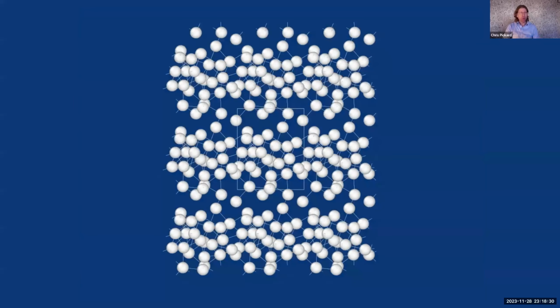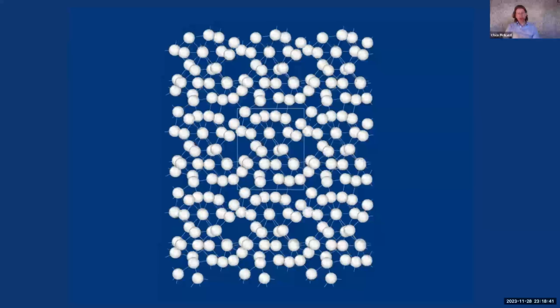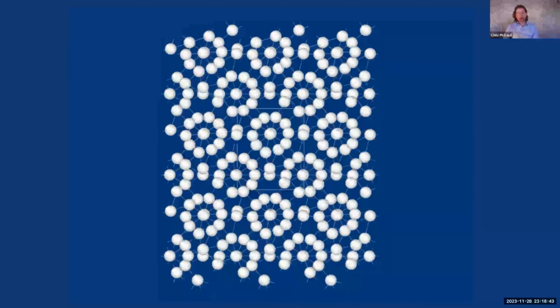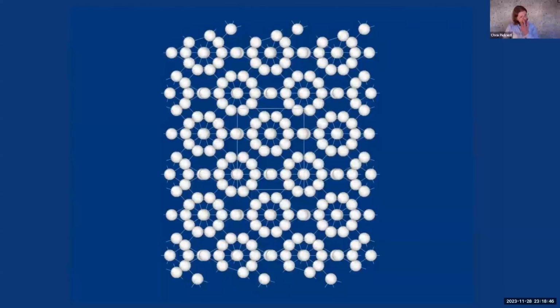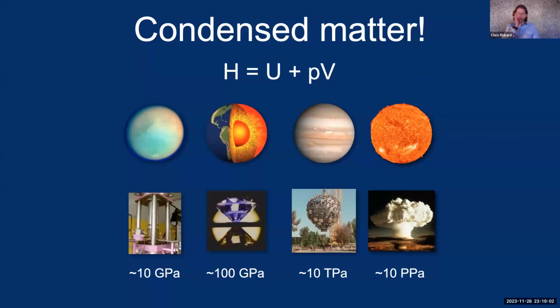Now, this is what in a large unit cell you'll often find. But in this case, 1 in 100 times, if you start from this random structure, for example, or others seemingly different, but with the same end point, you get an optimization that looks like this. So it looked completely random to start with, but it was just in the right initial random conditions that when it relaxed, the atoms clicked into these beautiful structures. This is the very famous gamma boron phase with its famous icosahedra of borons and dumbbells of borons, and there's charge transfer between these different units. Very beautiful crystal structure.